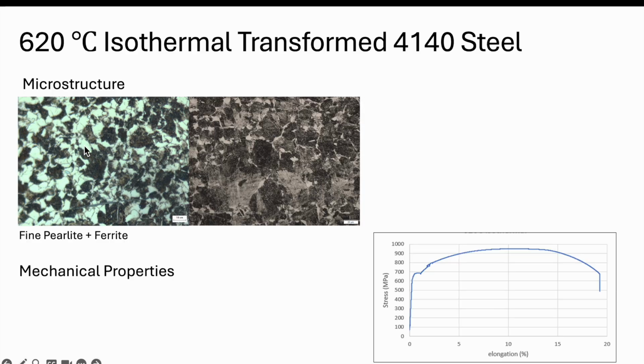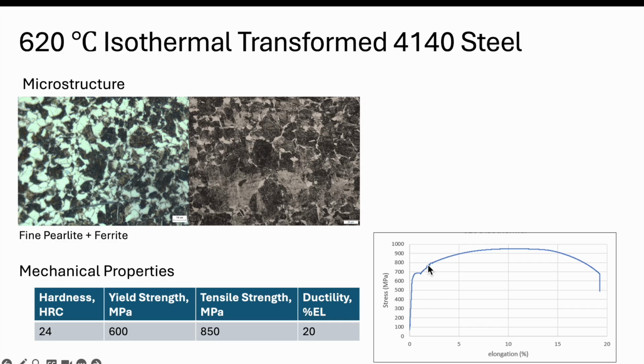All right, so what are the properties of this then? Our mechanical properties taken from the engineering stress strain curve look like this. One thing to note is that you have this here. This is more of a yield point phenomenon, and this is indicative of pearlitic or pearlite-based steels. From the table that we see over here, strengths are even lower. So yield strength is 600, tensile strength 850, and the ductility goes up.